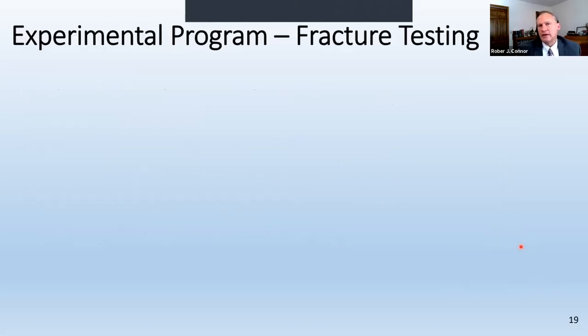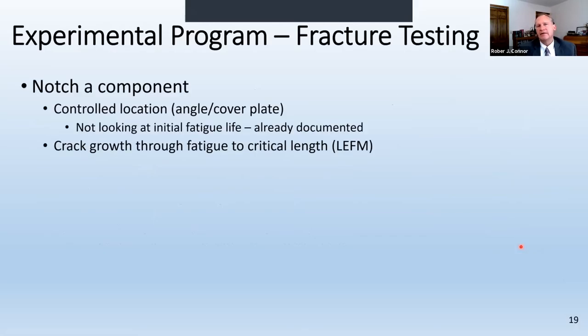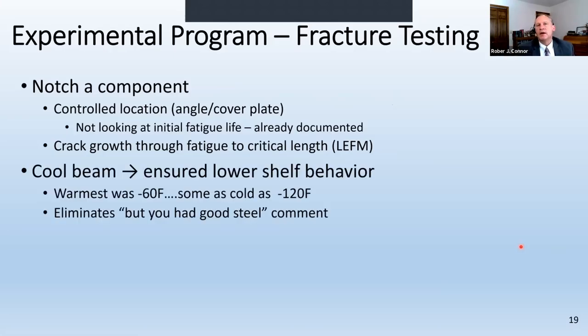So the experimental testing program was a lot of fun because we needed to test large scale, really full scale components. And so we weren't concerned about initial fatigue life, that's well documented. So we would notch a component, sharpen fatigue cracks in the specimens. We would then cool them and we would get them very cold. And the reason is we wanted the specimens to be on the lower shelf toughness because we didn't want to have anyone say, well, your experimental data are because you had very tough steel. So all of our steel was brittle, single digit lower shelf foot pounds or even joules, down to minus 120 Fahrenheit at times. So very, very cold.